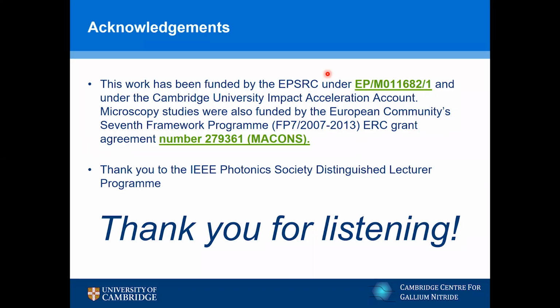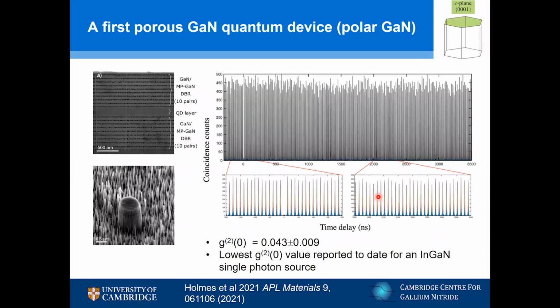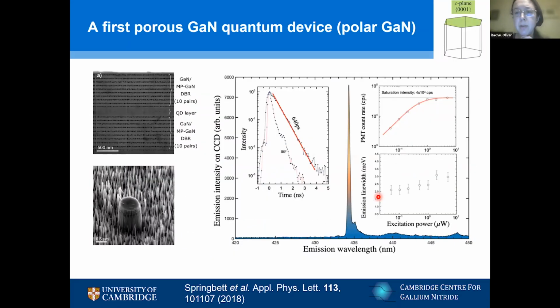Now, in terms of the power level, what kind of power are we seeing in those devices? I don't know if I can really talk about it in power level. We probably talk more in terms of counts per second, so number of photons per second. This particular quantum dot is saturating at about 4 times 10 to the 4 counts per second, and that would be pretty typical. So tens of thousands of photons per second is what we're managing to get out of these devices so far. We should be able to get higher than that because the emission rates are much higher. It's really to do with perfecting the extraction efficiencies. Okay, thank you very much.